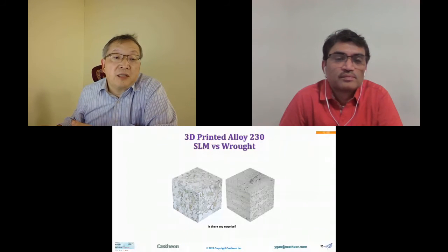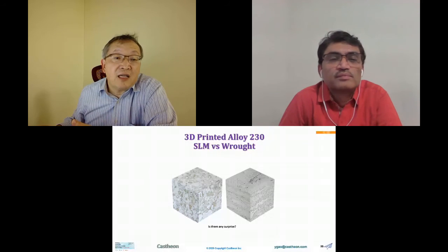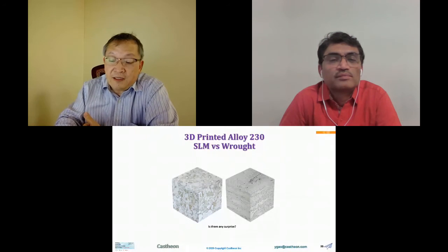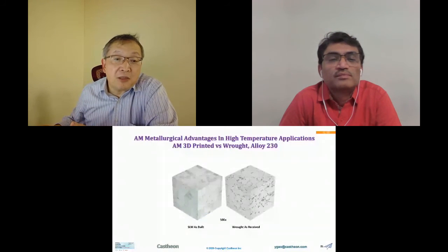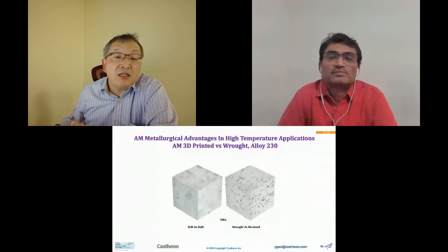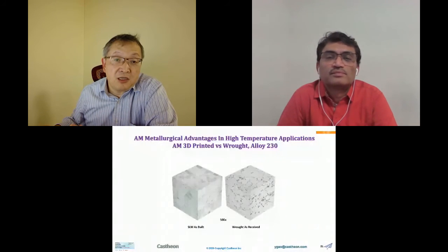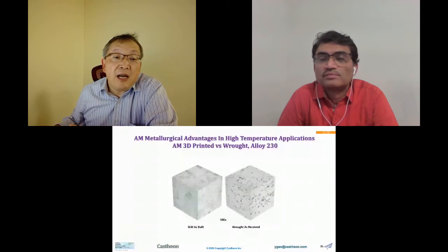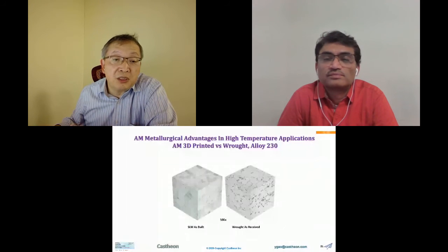The other thing we explore is to find the strengthening mechanism. This is the Haynes alloy, Haynes 230. On the left is additively made. The Haynes alloy has 14% tungsten and high carbon. So this material is strengthened, in addition to solid solution strengthening, by the stable carbides. In the wrought form, the carbides have already formed. In the additive form, the carbides and the tungsten truly stay in solid solution.